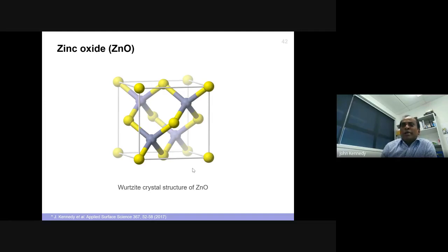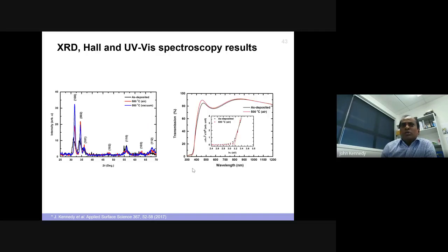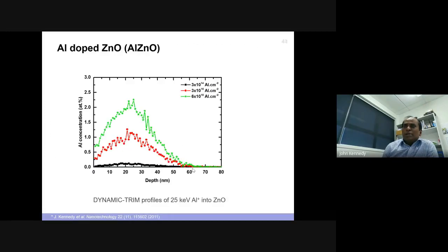And so it's easy to dope, and when you make zinc oxide films, it forms a preferential orientation of the C-axis, which is easy to manipulate. You can anneal in air or vacuum, and you can tune the crystal structure. Its transmission is more than 80% in the visible region. So these are transparent as well. That's the beauty. So then we thought, okay, in order to improve the carrier concentration, let's dope aluminum.